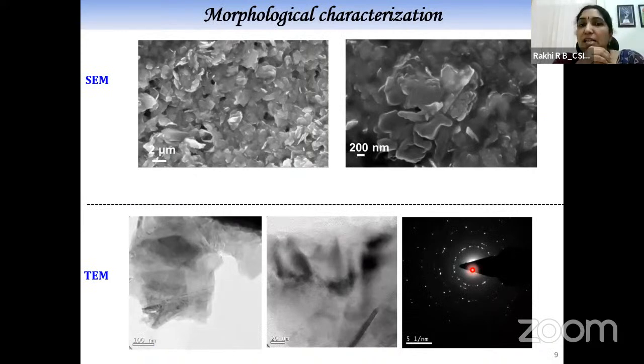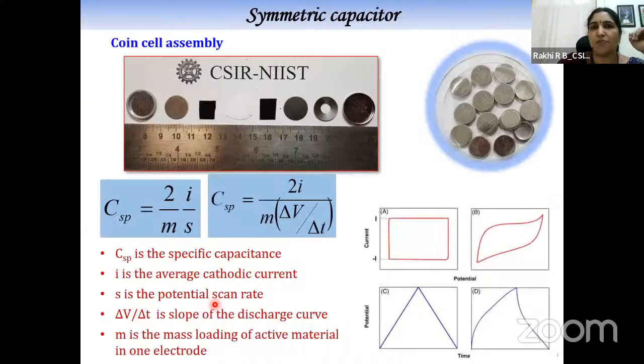Then we did surface morphological as well as microstructural analysis. Morphology gives some flakes of MoS2. And from TEM microstructural analysis, we found that the MoS2 is in sheet form, and that few-layer MoS2, 3 to 4 layers, is achieved.